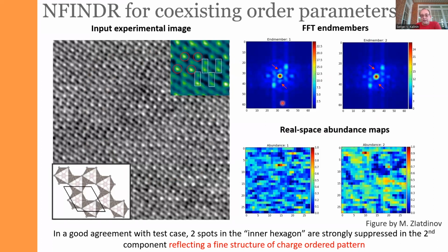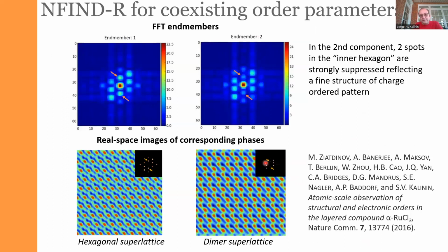So why does it happen? It happens because in this particular case, we deal with a system which has so-called nanoscale electronic phase separation. So physicists, based on the scattering data, speculate that it should have the nanophase regions of the different structure. But of course, the evidence for that is indirect. It comes from the scattering methods. And once we do this transform, we visualize what these regions are. And of course, the nice thing about the Fourier transform is that we can invert it.